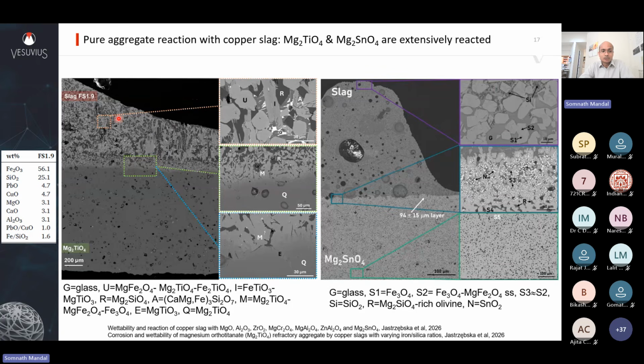Magnesium titanate, if you zoom in into the slag, you see a lot of these phases. You see U phase, which is ulvospinel, solid solution with magnesium ferrite and iron titanate. And you ask yourself, where is this titania coming from? Where is this magnesia coming from? It's coming from the substrate. And this is bad news because your substrate is getting heavily dissolved and reacted into the slag. Also, you see that you have formed iron titanate and magnesium titanate solid solution, this I phase, elongated ones. Again, your magnesia and titania are getting dissolved into the slag. You're forming forsterite. This is all bad news. You don't want any of these in the slag. And deep into the interface, you see also reaction, but it has slowed down because here the slag is saturated with magnesia, and then deep into the refractory, you see the pristine unreacted magnesium titanate and then MgTiO3, which is a common impurity in Mg2TiO4 based refractories.